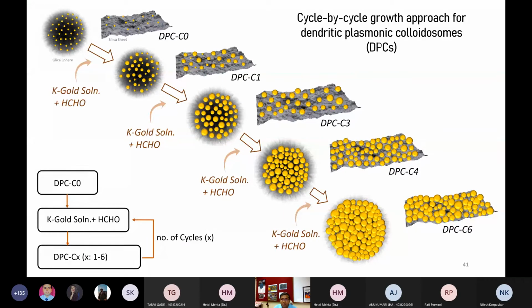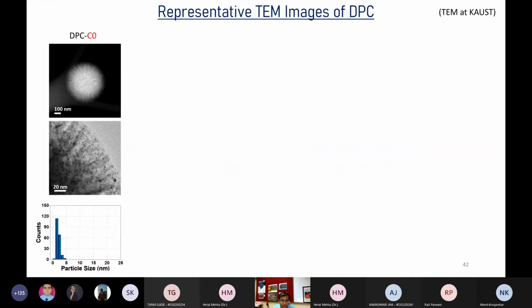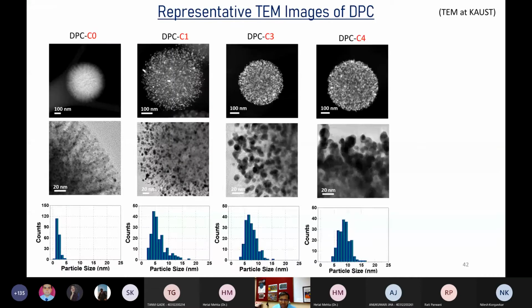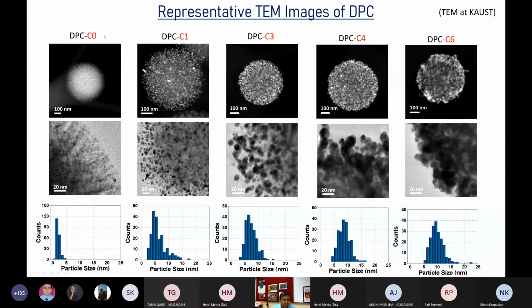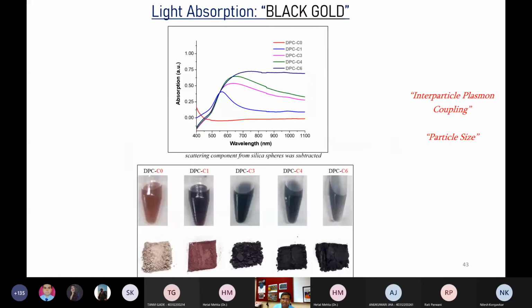So we decided to make the material with the different gaps and then find out which one is the best. So that's why we made C1, C3, C4, C6. These are the representative, we made more. And these are the TEM images also indicating that when you go from C0 to C1 to C3, C4, C6, the particles are coming closer and closer, and in C6, they connected with each other. And this is very interesting data.